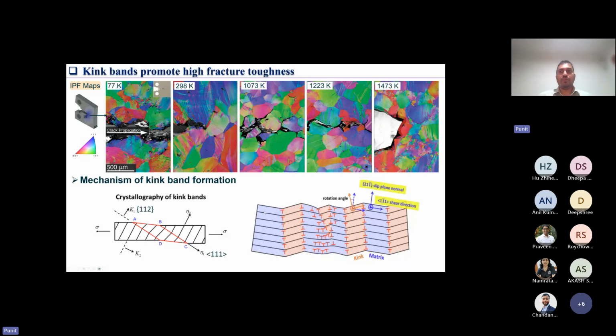Essentially, kink band formation is a strain localization process by which you get strain softening. But in this case, you can see that at all temperatures, formation of kink bands is the process by which the damage is spread away from the crack tip, giving you such high fracture resistance at all temperatures. Even at high temperature, where you can see intergranular fracture, you can also see formation of these kink bands. Although your grain boundary has weakened by exposure to oxygen, you can see this plasticity, and that's why you have such high fracture resistance in this material. At 1200 degrees C, we saw recrystallization started, which means the microstructure is not really stable at 1200 degrees C, and that's what gives you such high blunting at 1200 degrees C.